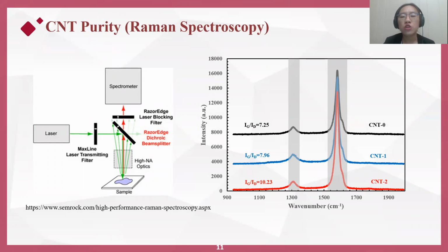Raman spectroscopy is a non-destructive chemical analysis technique based on the interaction of laser with the chemical bonds within the sample. For carbon materials, focus is normally placed on the sp2 and sp3 hybridized carbon. The G band at approximately 1585 per centimeter is characteristic of the ordered graphitic structure, and it corresponds to the carbon atom vibrations along the CNT axis. A disorder-induced D band at 1310 per centimeter indicates the relative amount of defective impurities or other symmetry-breaking defects, especially amorphous carbon in our case. Therefore, we use the intensity ratio of the two bands, IG over ID, as a direct measure of the CNT quality.